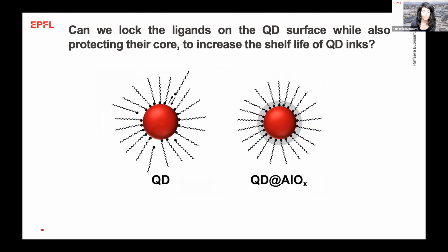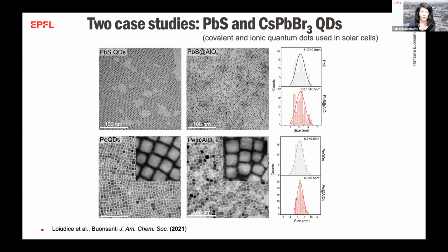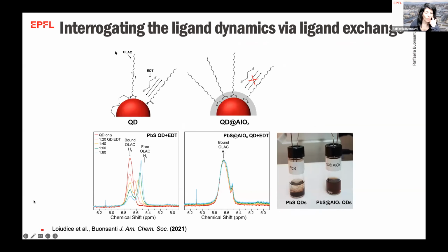Then, okay, we go back to our original question, if this thin oxide shell could actually lock the ligands in place. And we took as examples two different case studies, which are lead sulfide and perovskite, two types of quantum dots which are largely used in PVs. Normally, these quantum dots, for example lead sulfide, have oleic acid on the surface. And when you start to make a device, you exchange your oleic acid with dithiol because you want shorter ligands. And your solution crashes here. And you can monitor the substitution of the oleic acid with the dithiol by NMR.